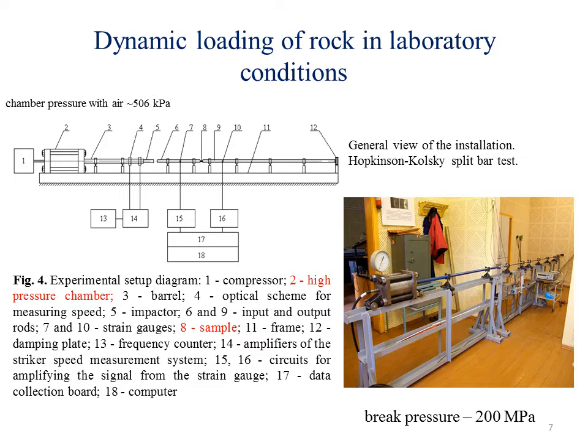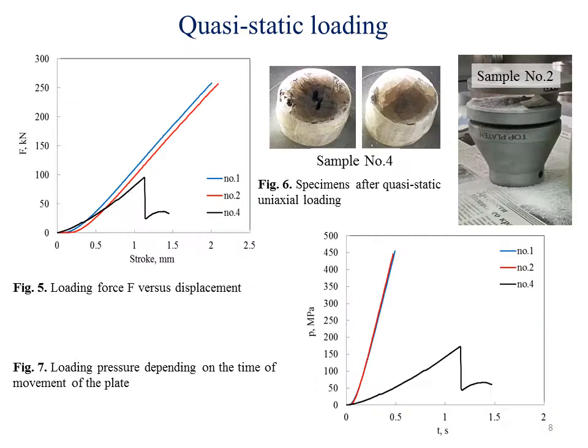Consider the case of dynamic loading of cylindrical quartzite. Air is pumped into the high-pressure chamber with the help of a pump to 5 atmospheres. After opening the valve, compressed air accelerates the impactor along the barrel. After the impactor collides with the input rod, a compression wave is excited in the latter. The compression wave is transmitted through the rod to the sample, after which, due to the difference in sound impedances, the wave decays into the wave that passed through the sample into the output rod and the wave reflected back into the input rod.